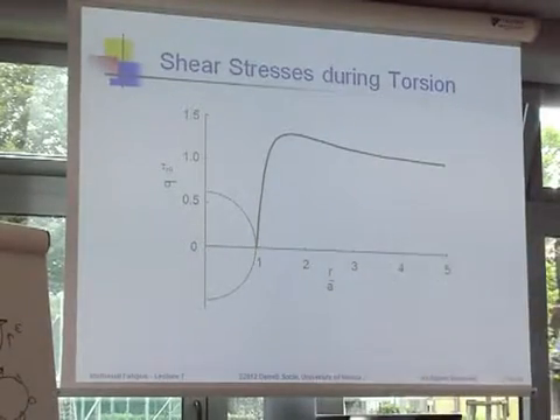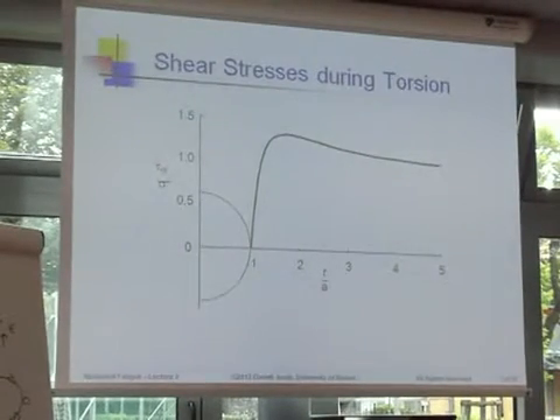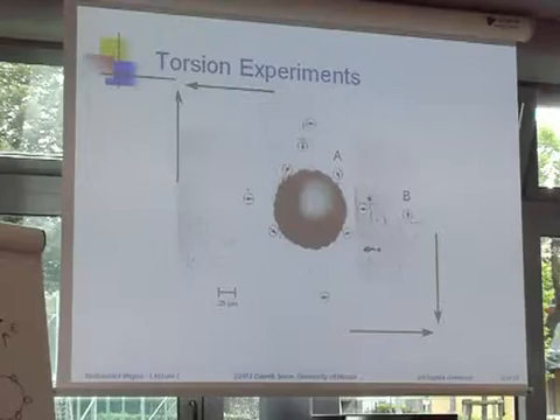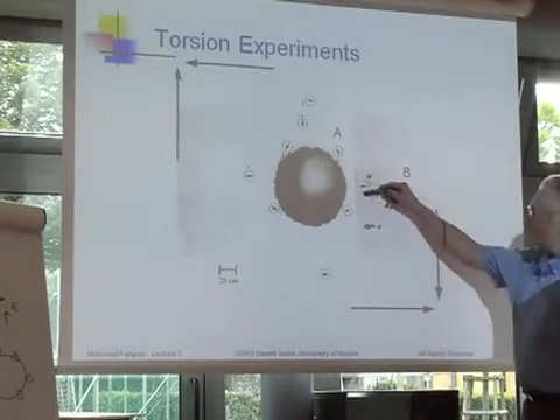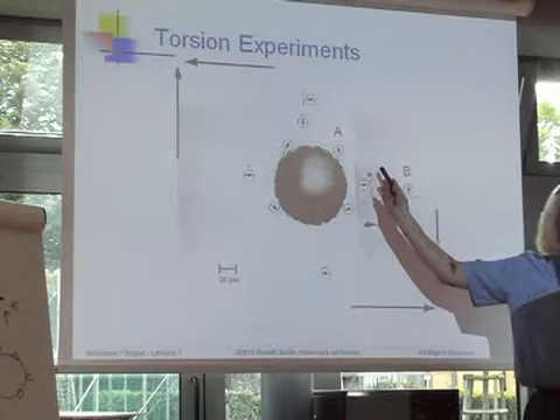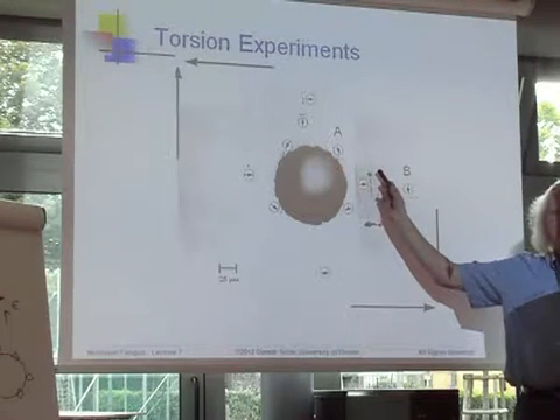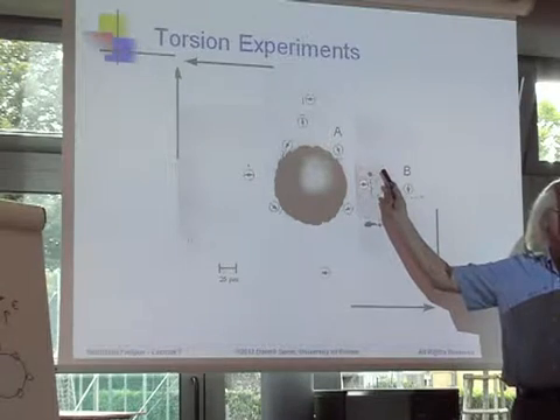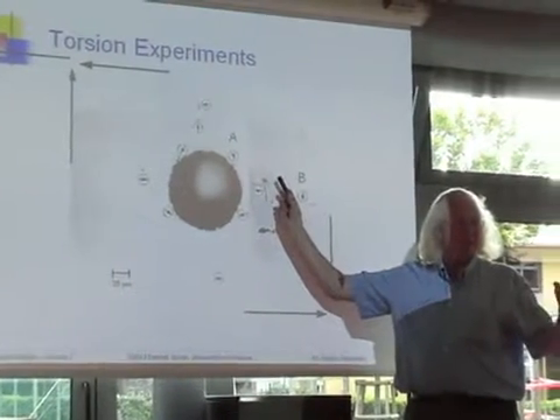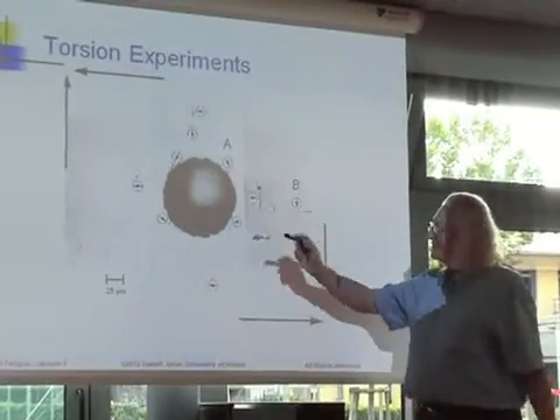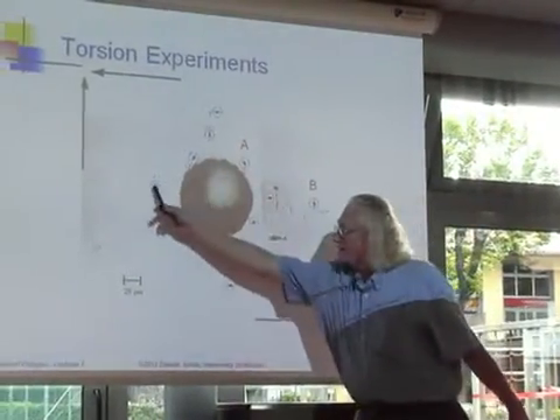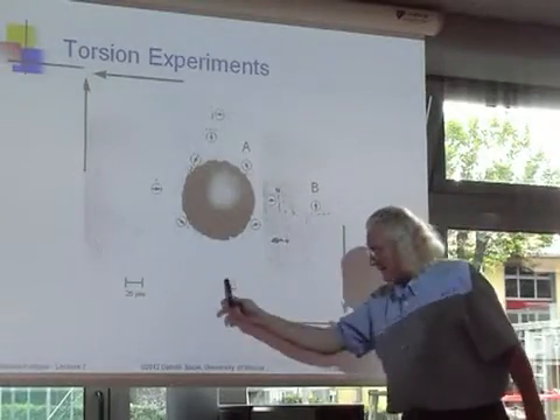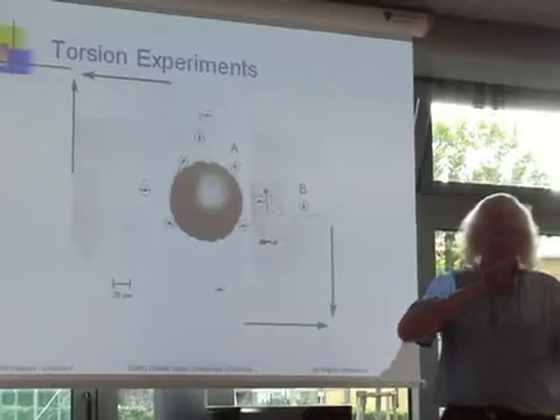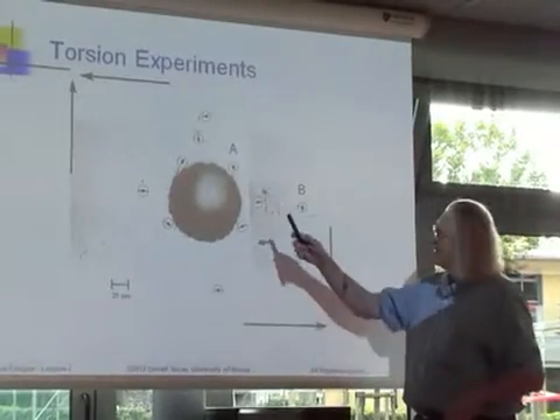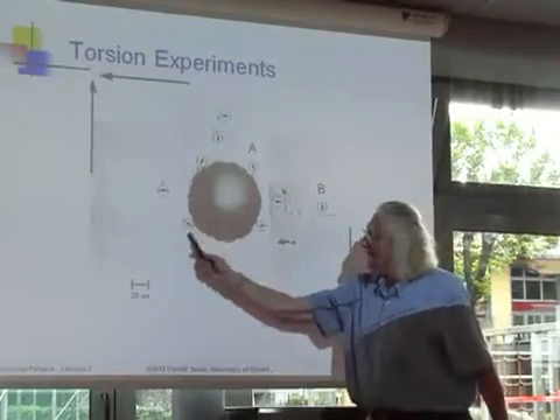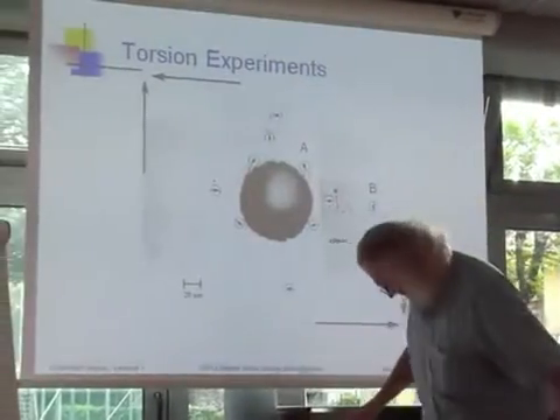Now, why is that important? Well, I'll show you this slide first. If you have a hole in torsion, frequently you get all the cracks to initiate out here. And people say, isn't that strange that the cracks initiate away from the hole? And this is a particularly important problem in rivets and aircraft. Frequently the cracks initiate not at the edge. And there's a crack here, there's one over there, there's one over there, right? One out here. And if you fatigue test this for a very long time, then you start to nucleate some cracks over here. Right? And those cracks come.